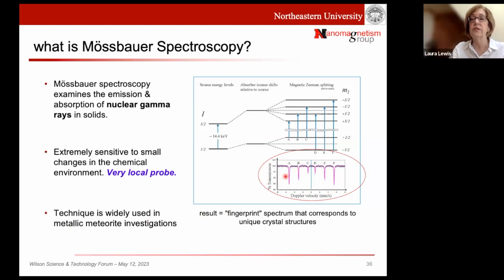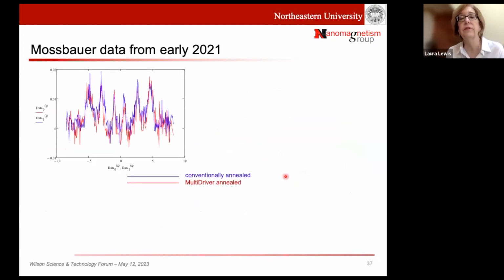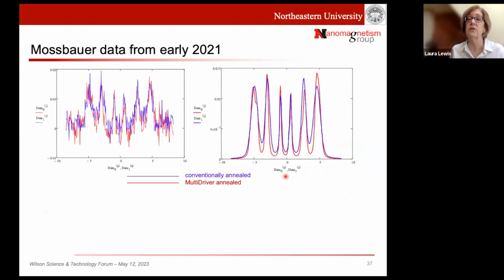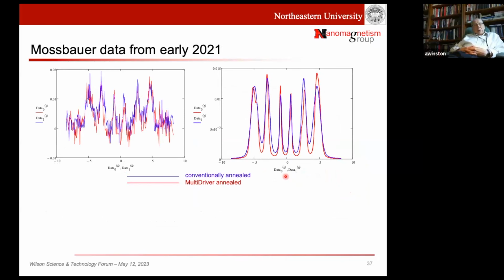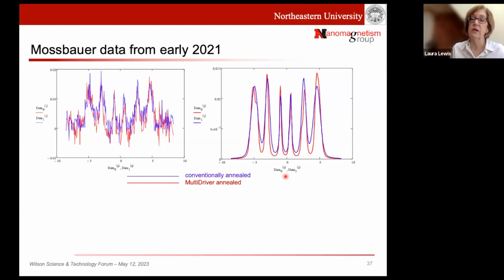But you get this absorption fingerprint that's very easy to analyze, and it corresponds to different crystal structures. So I gave these materials, instead of coming back to the US, they went from England to Ireland. And then we started looking at them, right around the pandemic. And the data here was not the data, but the acquisition, because my colleague and his family got COVID, and it was a lot. So my colleague, Plamen Stamenov, is a physicist at Trinity College in Dublin. He called me up. He said, oh, Laura, you've got tetrataenite. I'm like, what? This was in 2021. And he sent me these data. And I said, that doesn't look like anything. I do not see any difference. But through what is standard in this procedure, once you process the data, you can see a very clear difference, red versus the blue, between the two samples, same samples, just processed differently.